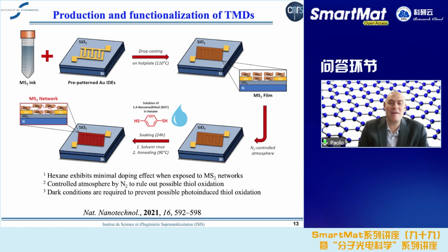Of course, you know better than me that the more you create larger polyaromatics, the more aggressive a solvent you must use, like chlorinated solvents, and this is not too good. So one has to find the right compromise, because the 2D materials are extremely sensitive to solvents that have a small dielectric constant.